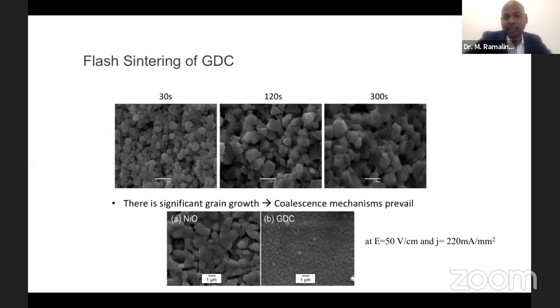You can see 30 seconds, 120 seconds, and 300 seconds, and then we can sinter the material at high temperature. This is a new kind of flash sintering, because there are nearly 5 groups only working around the world on this kind of sintering. So we are also working on flash sintering.